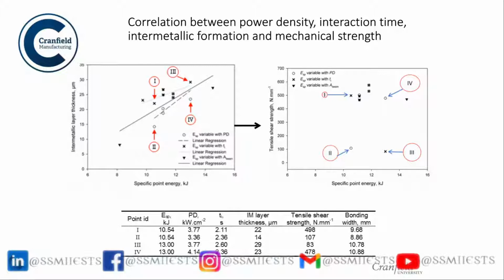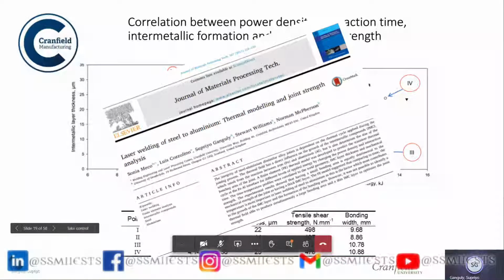I will just draw your attention to this point 2, where you will see that the intermetallic layer thickness is quite small or low as compared to the others. So this is kind of best. However, the tensile shear strength is very poor, and this is because the bonding area is poor. So it is not only the intermetallic that decides everything, but also how much bonding area you have. And this particular combination was found in this work and explained in this particular article, which is written by my student Sonia.